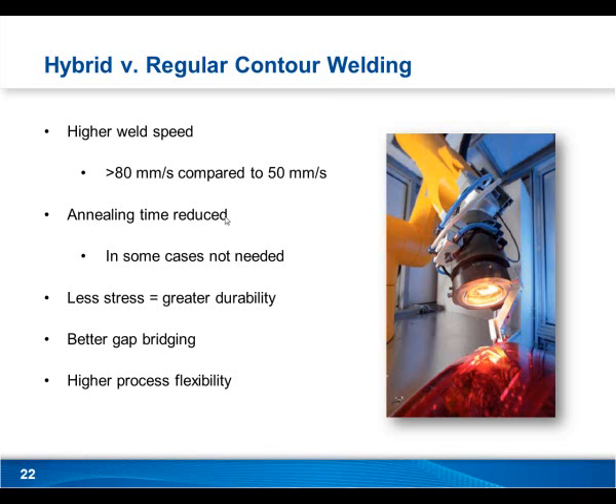So essentially the lights are baked in an oven for a certain amount of time depending on the way they were welded. But because the halogen radiation is softening the plastic, that annealing process is taking place during the weld. So a lot of that can be reduced, and in some cases it's not even necessary after the weld takes place. Also, there's less stress compared to contour welding as far as thermal stress.